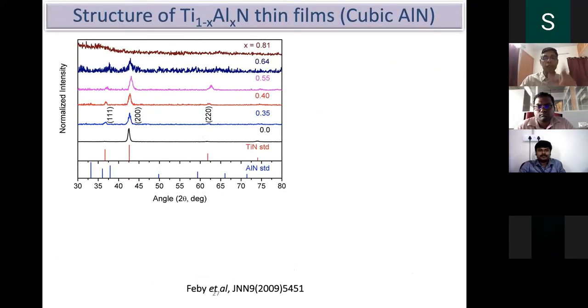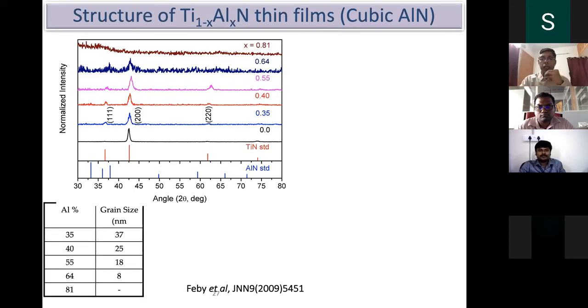Okay, this is what I said, that cubic aluminum nitride. There is a slight deviation, but I just wanted to show you how the cubic aluminum nitride can be grown. We have grown one more offshoot of aluminum nitride. If you add titanium with higher percentages, you can see titanium nitride peaks, and finally it goes to amorphous when you incorporate the aluminum into the system. This is basically titanium nitride. What happens around 64%, it becomes amorphous, and then complete amorphous is seen in the case of 0.81.